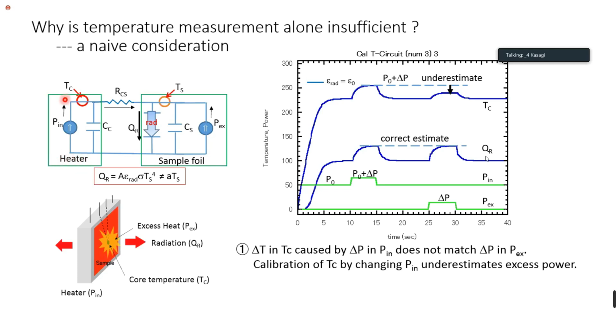One is from the heater, and another heat flow is coming from the surface. If excess heat generation occurred, the heat flow is coming from this side. My question is, we usually do the calibration by just changing the heat flow from the heater. Is it enough? So I just calculated, though it's a very simple calculation. Here you have a delta P in, the input power, and the core temperature is changed by just this. Is it the same as the temperature change if the excess heat comes from the other side?